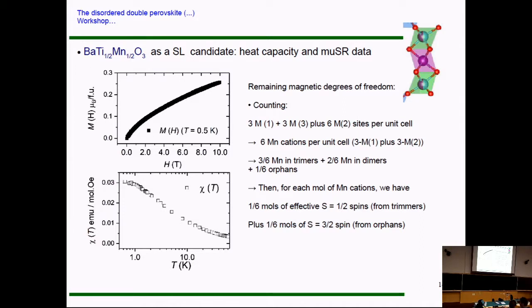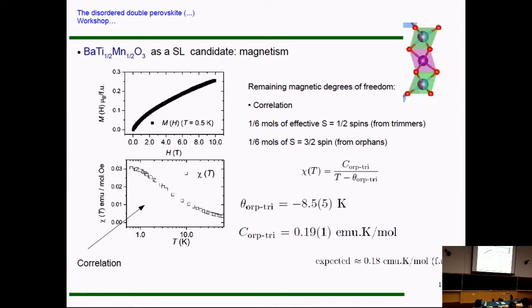Then for each mole of manganese, you have 1/6 moles of effective spins 1/2, because if I have 3/6 trimers, for each mole of trimer I have 1/3 moles of effective spins 1/2, plus 1/6 of S equal 3/2 spins from the orphans. So these are the remaining magnetic degrees of freedom, and these are the degrees of freedom responsible for the magnetic response at lower temperature. So we decided to test this idea, and we fit the susceptibility down here with a simple Curie-Weiss behavior, just to see if the numbers turn out to be at least reasonable.